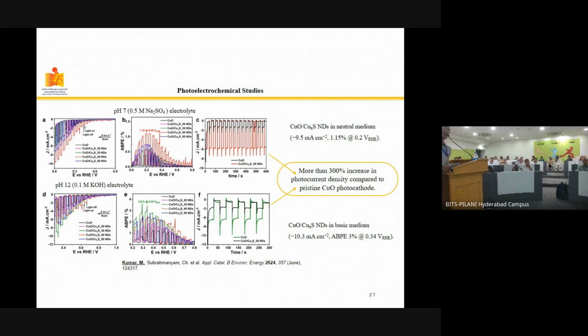Then, as you've seen in the earlier cases, the activity is going to be improved, and at one point you see that this is an optimized one. It shows good activity and you have very good currents, and it works well over a period of time. That means if you look at the combination, you get good currents under these conditions, and these improvements are significant when you compare with only copper oxide based, which is what is known in the literature. Copper oxide combination, as I mentioned, copper +2 or copper +1, these are the good combinations of p-type materials. So we are trying to strengthen this combination.